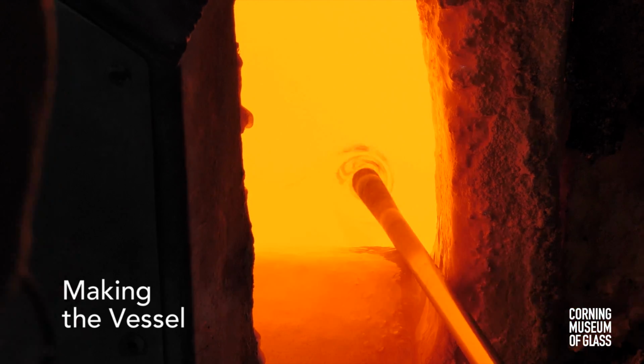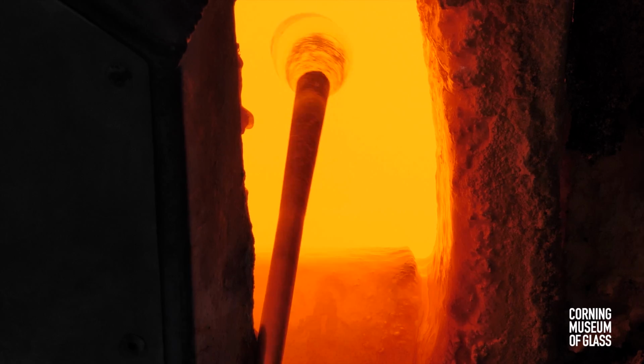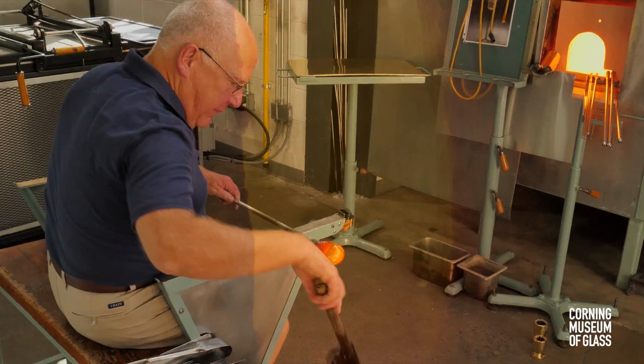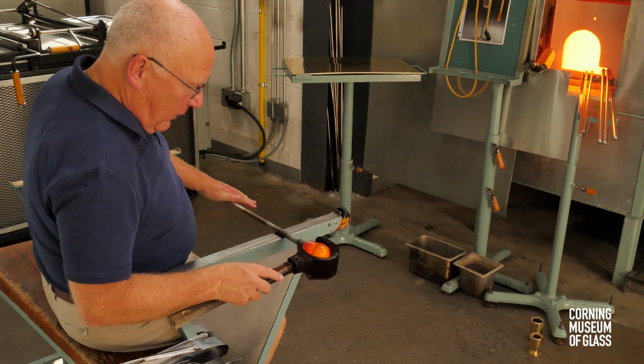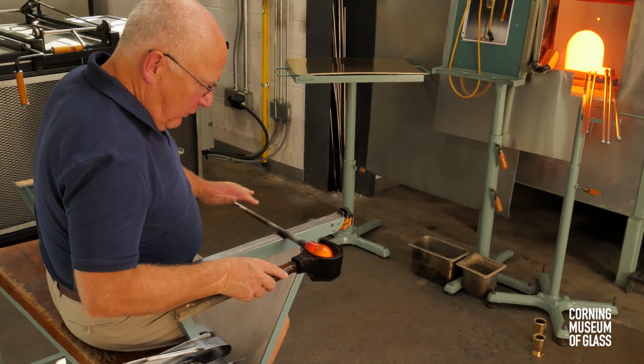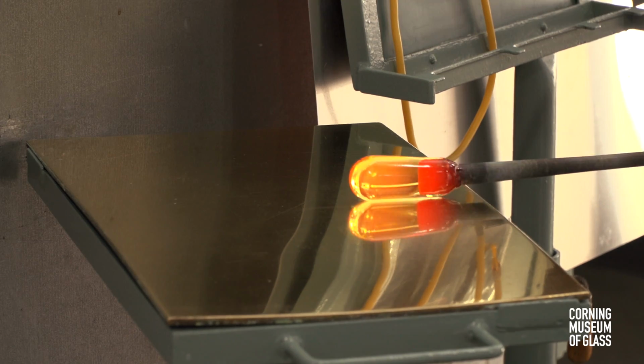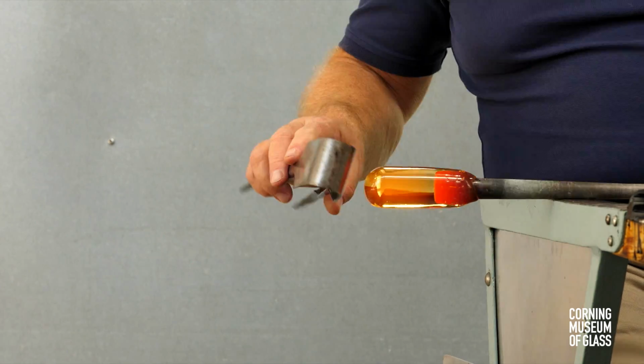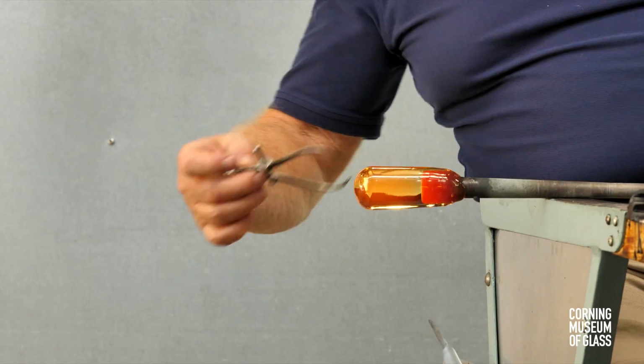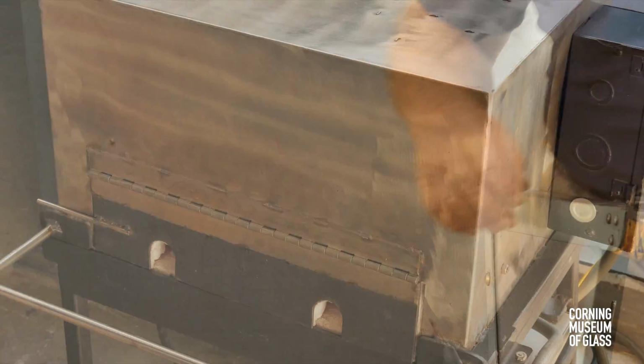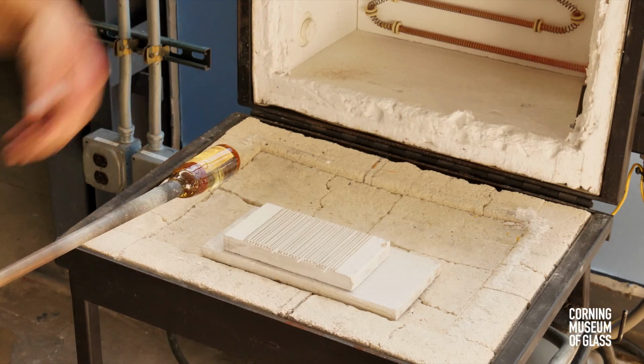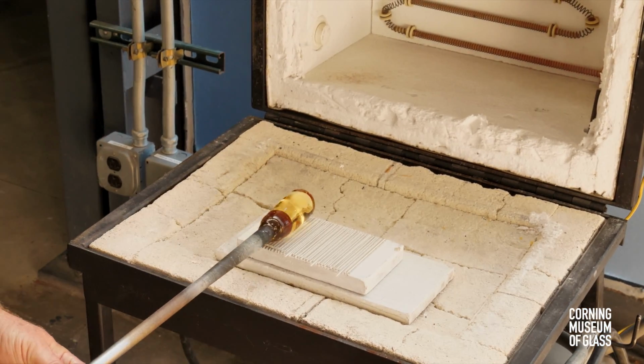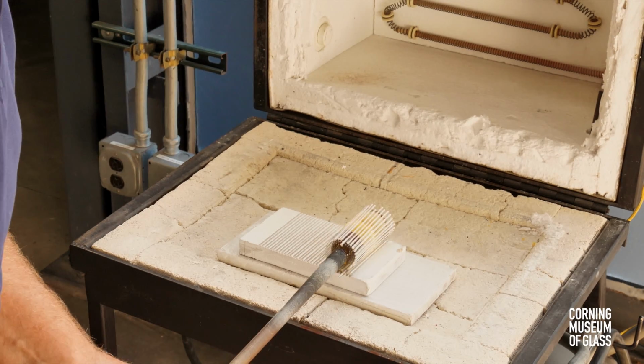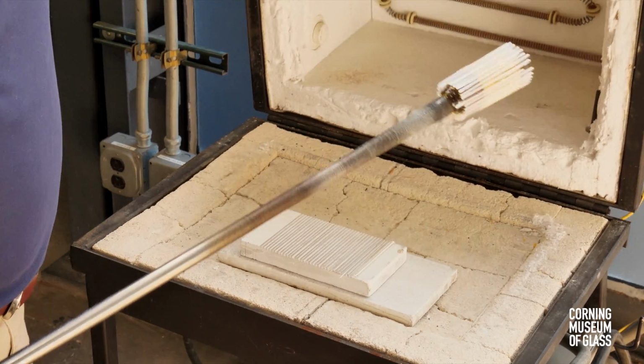The vessel body begins with a gather of transparent glass. This is blocked to create a spherical shape and then rolled back and forth on the metal table, the marver, to produce a cylindrical shape. Its diameter is carefully monitored and altered to correspond to the length of the roll-up of canes. They've been placed on a ceramic plate, heated to about 1400 degrees Fahrenheit, and they stick to the clear glass.